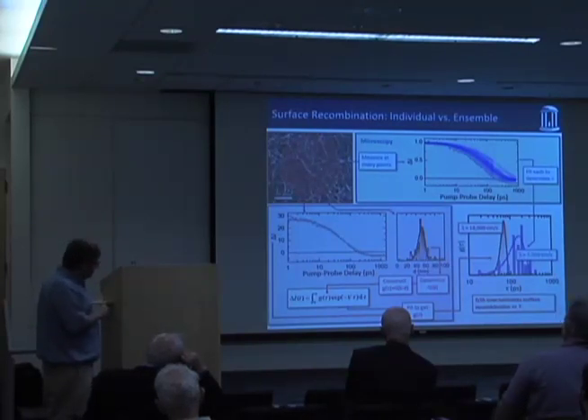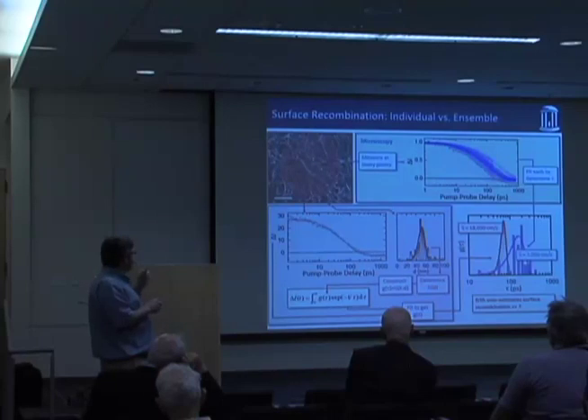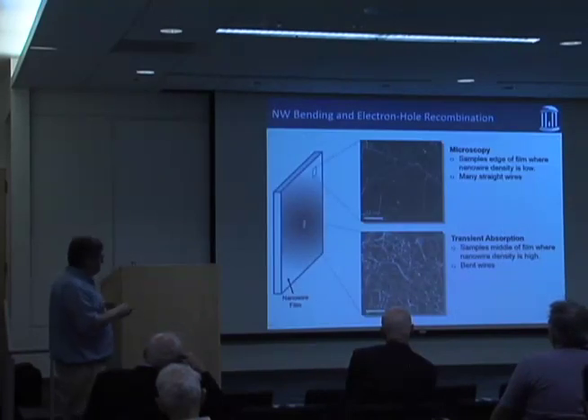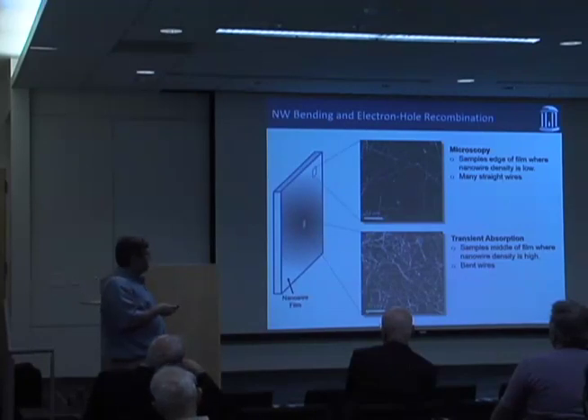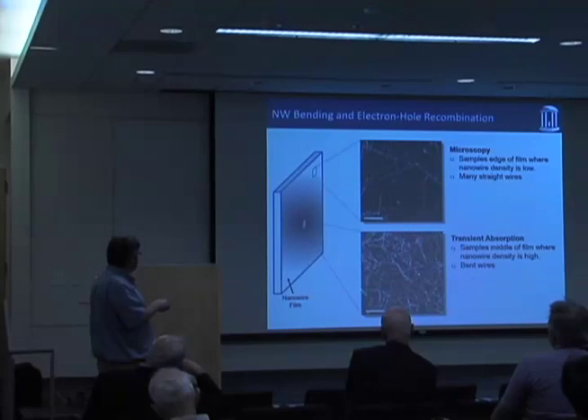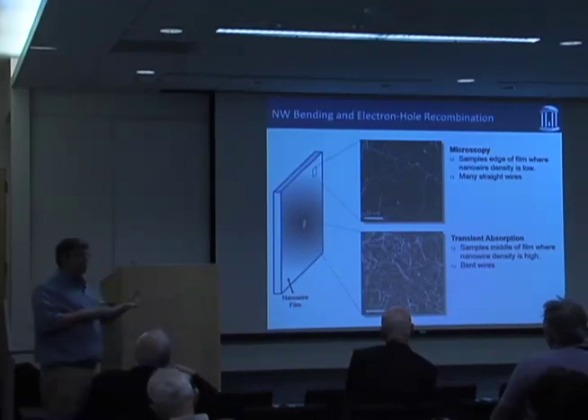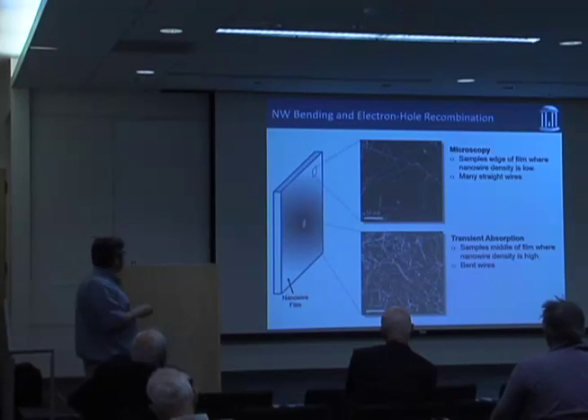And so we started to think about what could be going on, and it turns out that yes, both experiments were done on exactly the same sample, but in order to do the transient absorption, we had to do that in a part of the film that had a lot of nanowires, because you had to have enough absorption intensity to measure it. And so that was in the center of the film, and that's what the SEM looked like from the center. But in order to do the microscopy, that was too many wires. They were overlapping. It was hard to make sense of what was going on. So we'd go over to the edges of the sample where there were fewer wires.